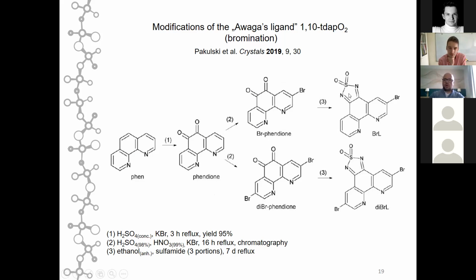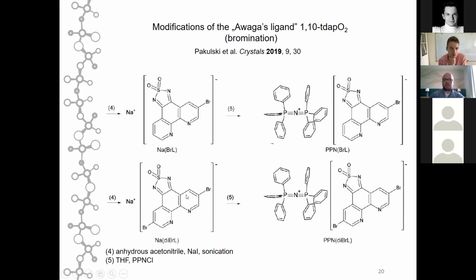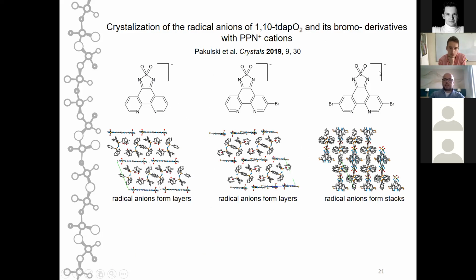You can close the dioxothiadiazole ring, you can reduce it, and obtain PPN salts of these radical anions. So we managed to crystallize all three, the unsubstituted, mono- and disubstituted radical anions with PPN cations. You can see that the crystal structure of these compounds leads to a layered structure where anions and cations are organized in layers. And this is the case for the unsubstituted and monosubstituted compound.